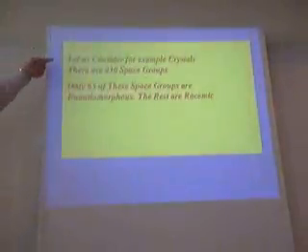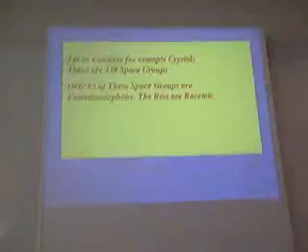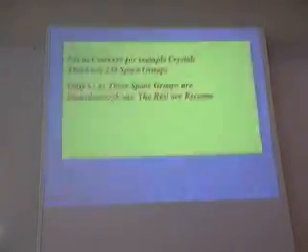For example, if you consider crystals, they can pack in 230 different space groups. But only 65 of these space groups are enantiomorphous. The rest are racemic. And even among these 65, some enantiomorphs are actually represented by different space groups, so even this number is lower than that. Therefore, the probability of a racemic or chiral molecule to crystallize in a non-enantiomorphous crystal is much larger than crystallizing in the enantiomorphous crystals.